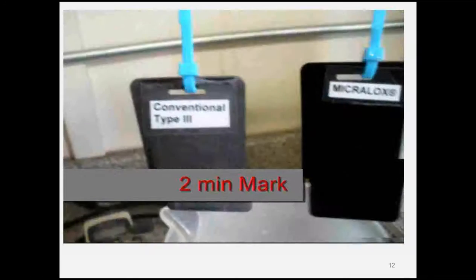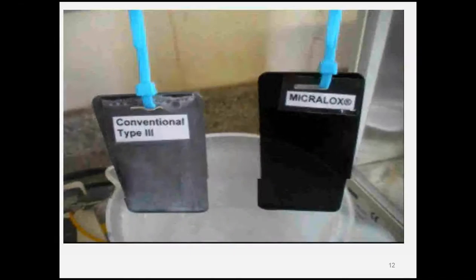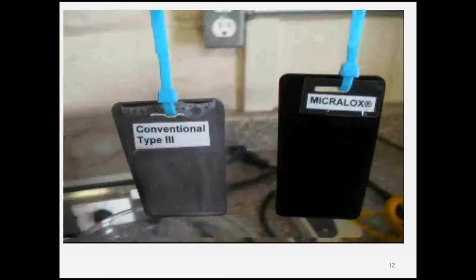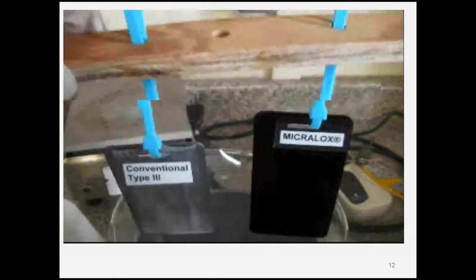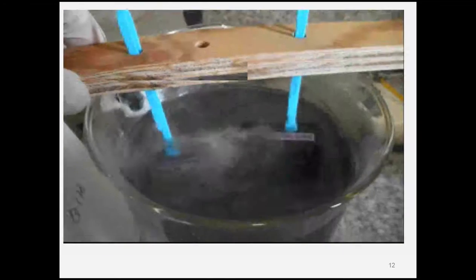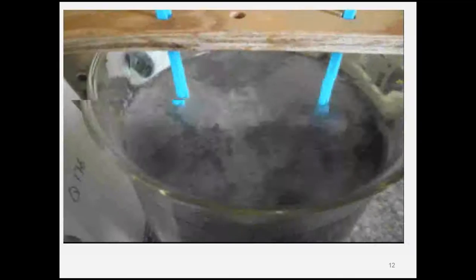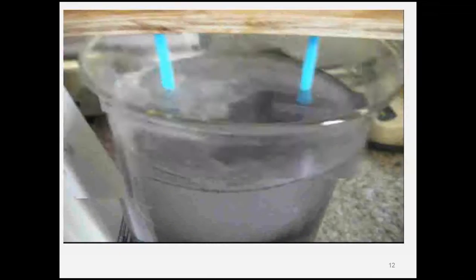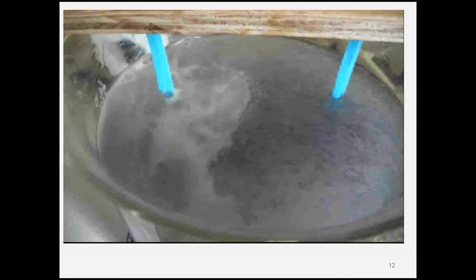So at the 2 minute mark, we can see some degradation on the type 3 coating. It may not look terrible, but it's clearly being attacked, while the MICRALOX coating is basically staying untouched at this point.